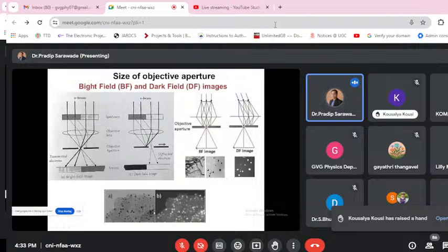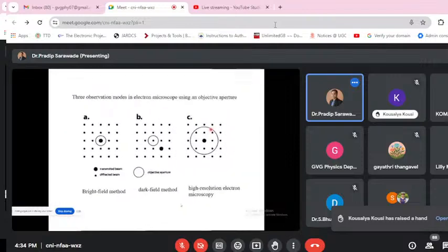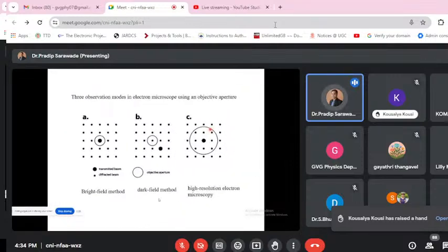Okay, you can see these are silver nanoparticles. This is a bright field image and a dark field image. So silver nanoparticles on the carbon surface appear as dark spots in BF images, and in DF images these silver nanoparticles appear as bright spots. Okay, so bright field and dark field, you understand.